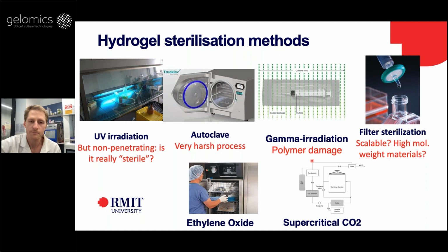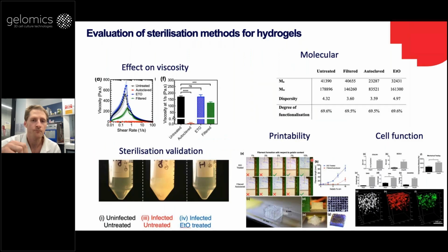So in this paper that I'll describe, we assessed 4 of these sterilization methods. We assessed them for their effect on viscosity, on molecular weight changes, and degree of functionalization changes due to the sterilization. We checked whether printability was maintained, and also cell function in terms of differentiation towards production of neocartilage. And we also validated the sterilization methods by deliberately inoculating with bacteria, sterilizing, and then testing whether there was any bacteria left over.